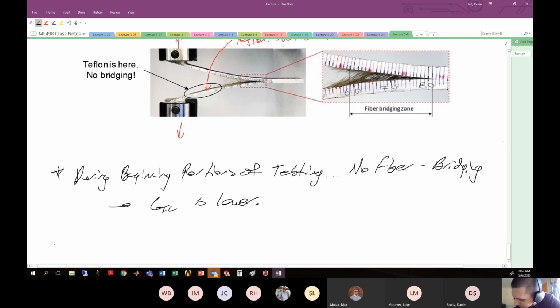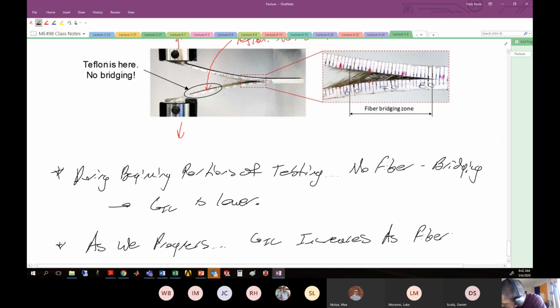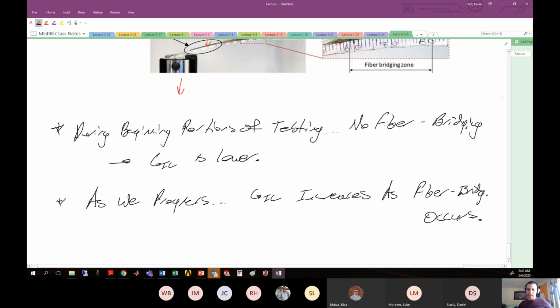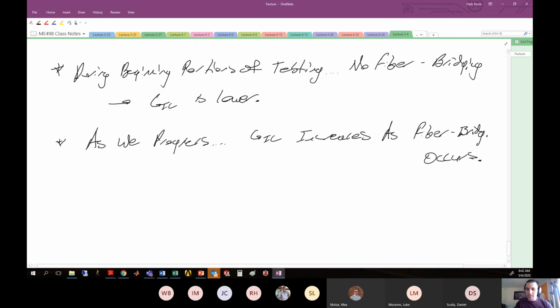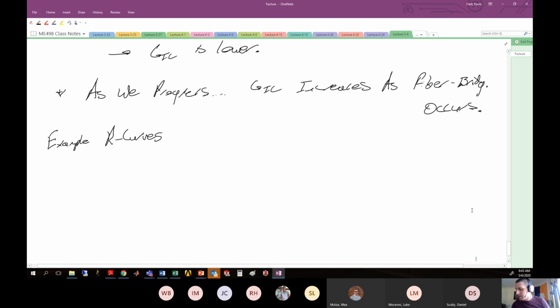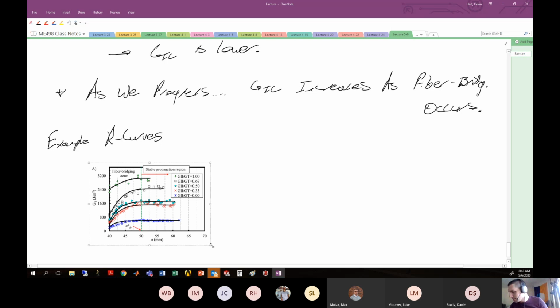So as we progress, G1C increases as fiber bridging occurs. Hopefully we can all understand that and follow that. Initially, there's no fibers bridging the crack plane, but as the crack begins to propagate, more and more fiber bridging will be apparent. Okay? So it results in R curves, which again is plotting the critical strain energy release rate as a function of crack advance. It results in these R curves that look like this.